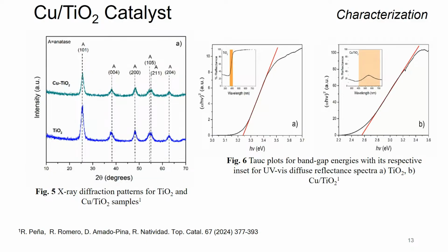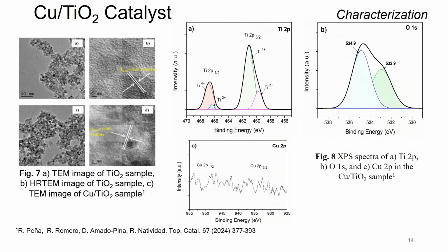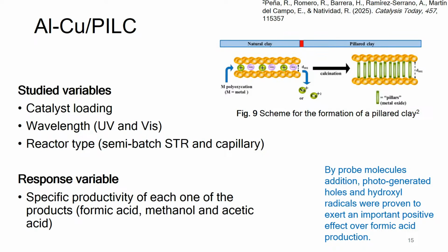But then when we added the copper, we obtained a decrease and it went down to around 2.6. So remember that we added copper for two reasons. One, to promote the conversion of the carbon dioxide or carbon species, and also to decrease the energy band gap so it can be activated by sunlight. By transmission electron microscopy, we obtained the interplanar distances that prove that there was anatase. And then by XPS, we also obtained the coordination of the titanium and copper. And that was one of the catalysts.